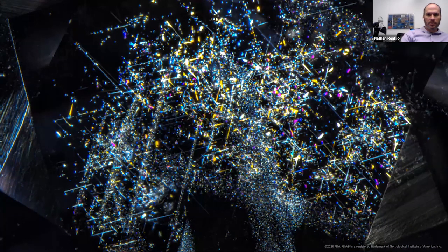When we look at these Montana sapphires from secondary sources, they generally have quite a lot of rutile silk in them. This second phase in the corundum can often have these rainbow iridescent colors. The silk is oriented in three basic directions, so it's crystallographically aligned to the host corundum. Silk is a pretty common feature in sapphires from a secondary source — and that's really important because that's what you need in your sapphire so that when you heat it, the silk gets dissolved into the sapphire and pairs with the iron to form iron-titanium pairs, which produce the blue color.